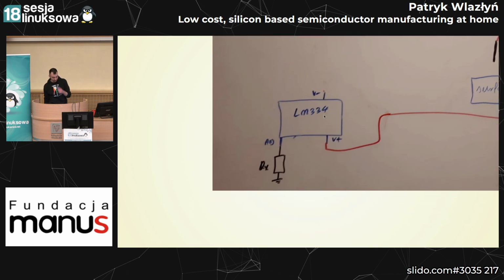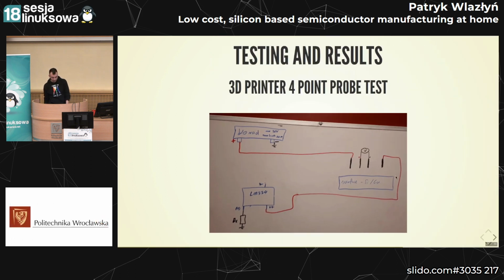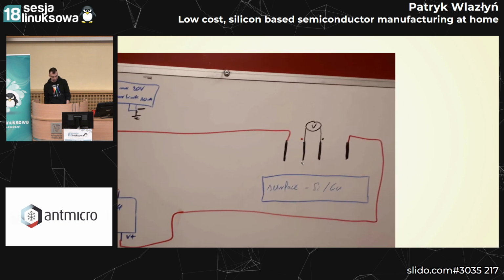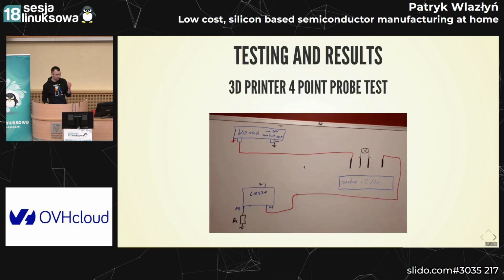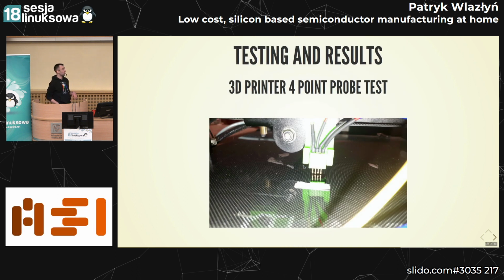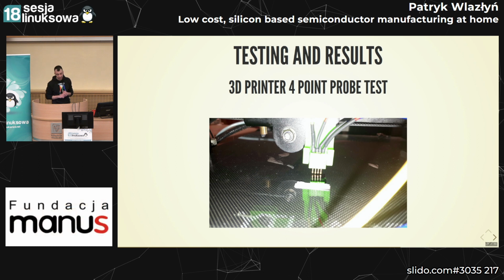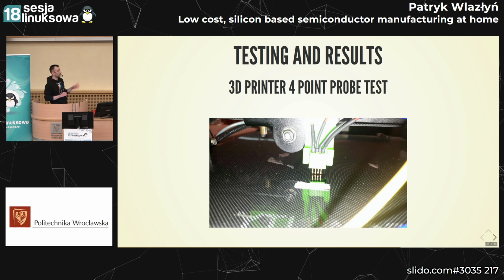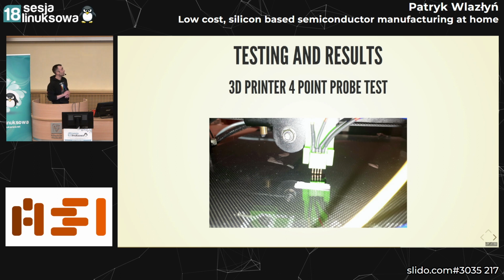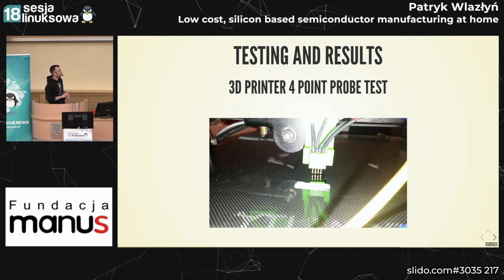This is the setup. You basically have a current source connected to one of the terminals, and the other terminal goes to the power supply, and you apply a voltmeter in between, and you can measure the resistance. The problem is that we actually didn't get good results, even though the setup looks very cool. For some reason, when you have a very low resistivity, the values that you're reading are all over the place, and we suspect that this is because we formed something called a Schottky contact on the top, which creates a diode in itself when making a contact between a metal and a semiconductor, which screws up all the measurements. But maybe we have to work a little bit more on it. We don't really have any good results doing this, although we spent a lot of time on it.